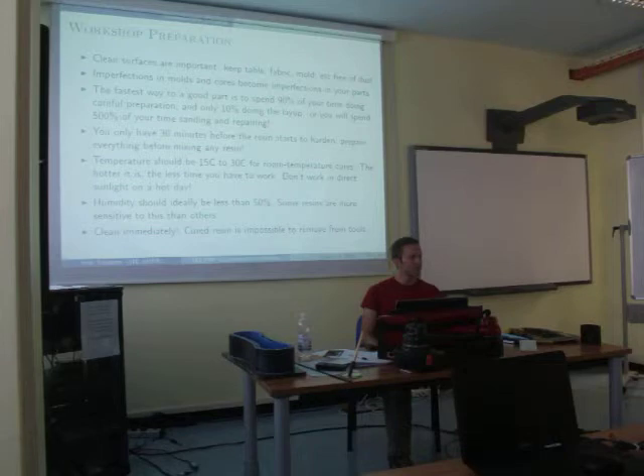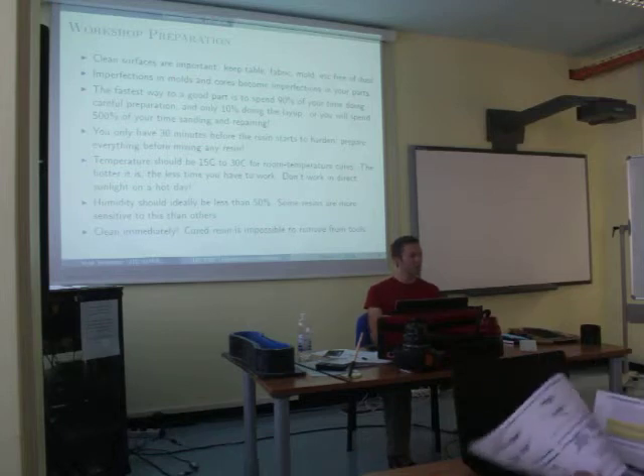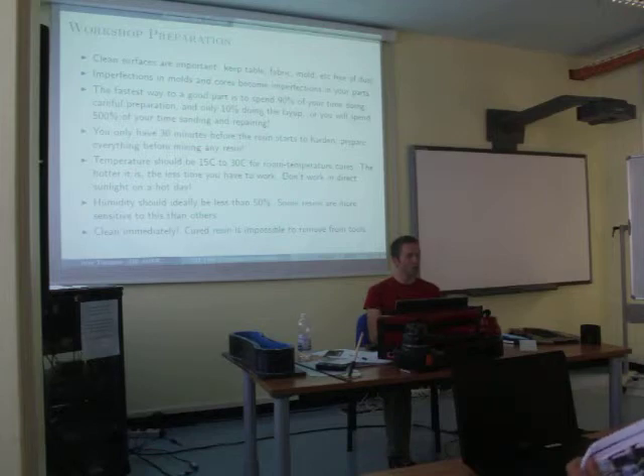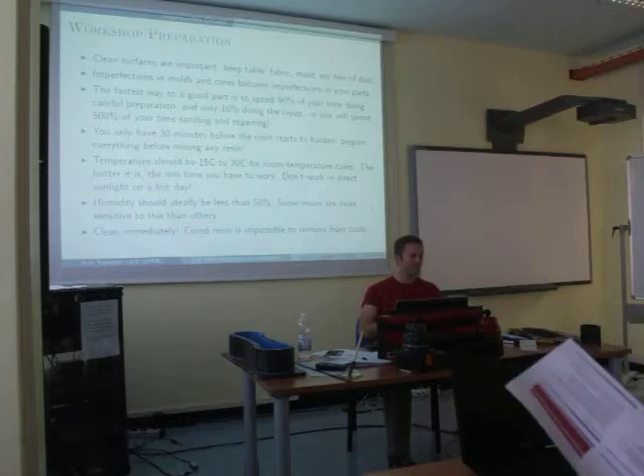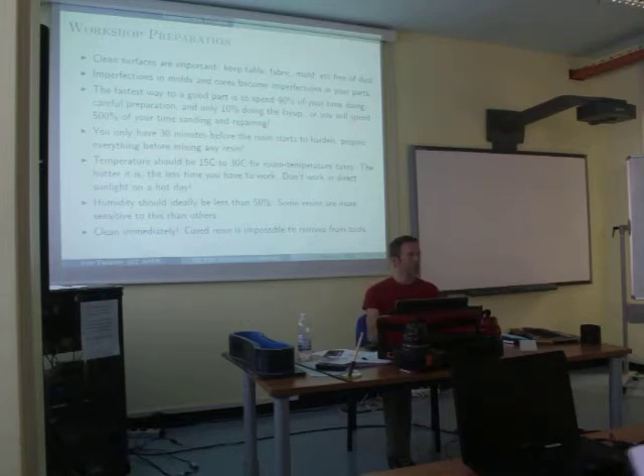Humidity should be less than 50%. So the best places are like in the desert, or they have humidity controllers. Here in Genova, we can't do anything about this. So we're going to have a layup tomorrow, and it's going to be like 80% humidity, and whatever. The reason you want the humidity low is when you put a vacuum bag around it, for example, the moisture will become a gas again. Any water absorbed by your resin will gas off as the pressure drops to near zero. The boiling temperature of water will become lower, and you get the water boiling off, and that creates bubbles in your epoxy, and it looks bad, and it decreases your strength.